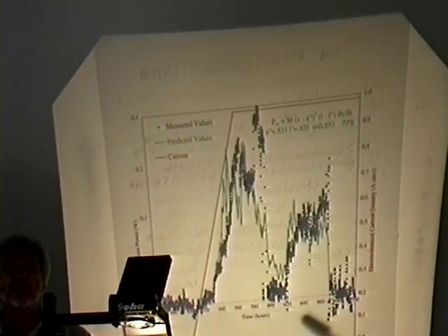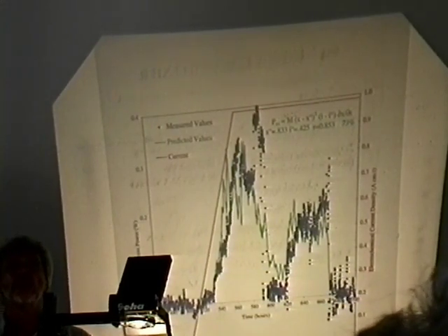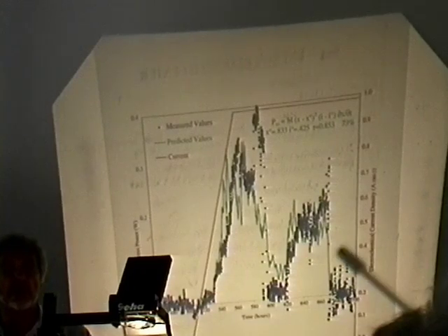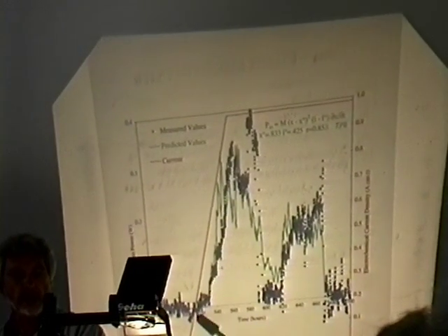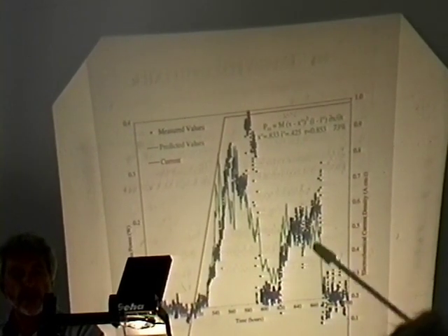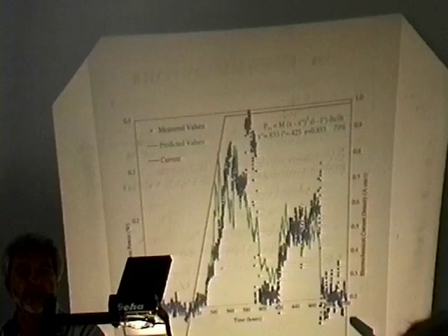in order to correlate the appearance of excess power with the three variables that we believe to be important: the excess loading, the excess current density, and the rate of change of the loading, that is the gradient, the flux of deuterium through the interface. But just concentrating on the blue points, we observed some excess power. So remember those two blue bumps.